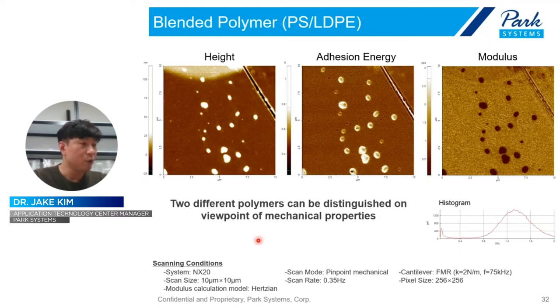And like these images, two different polymers can be distinguished from the viewpoint of mechanical properties using pinpoint mode. In this one, the substrate is PS, polystyrene, and the bulk modulus is about 1 or 2 gigapascal. And this bright dot is LDPE, low density polyethylene. And the bulk modulus of LDPE is around 100 megapascal.